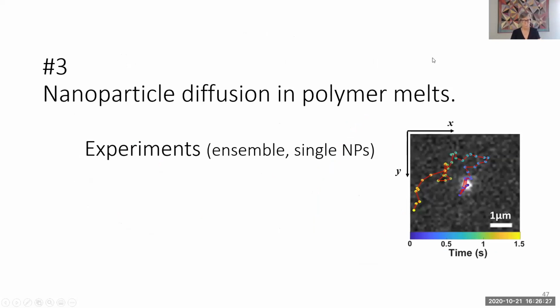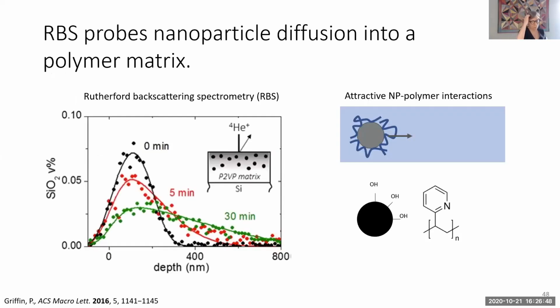Okay, in the last few minutes, I just want to share what we've done with particle diffusion. And so the first set of experiments are going to be about an ensemble where we look at a whole bunch of nanoparticles moving. And then like it's shown here, the single particle tracking where we're looking at one particle moving at a time. Okay, so first with the ensemble, this is another ion beam method. It's a little different in the sense that we now have a composite and it's on top of a homopolymer. And we look for the particles to diffuse in, right? So as a function of temperature and time.